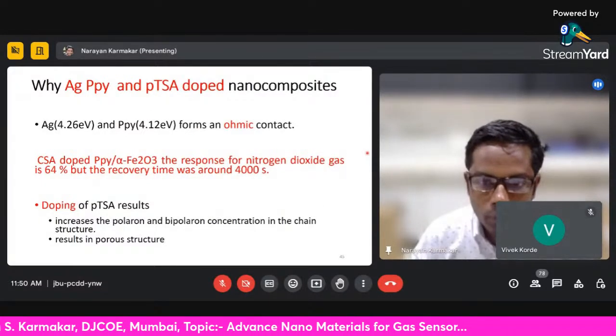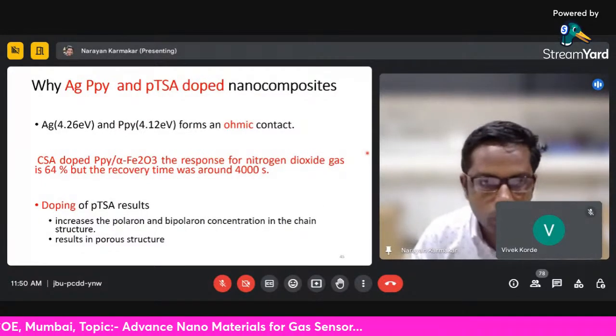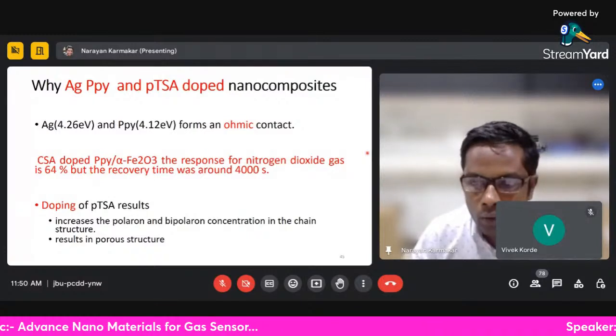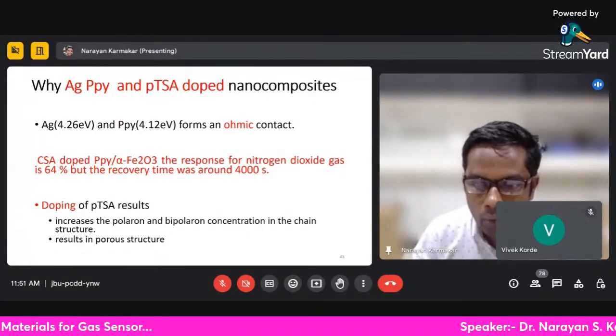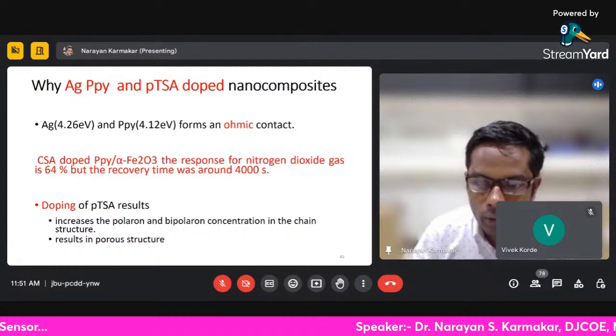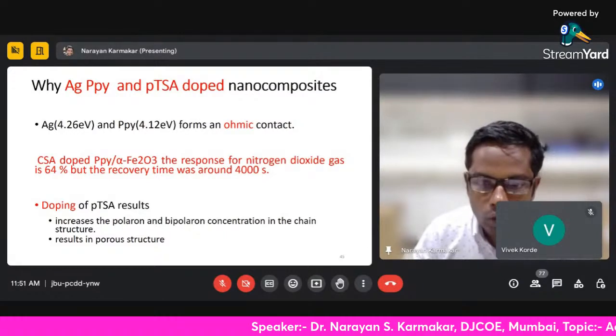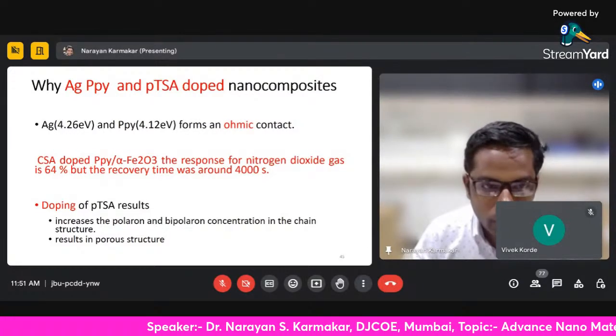Polypyrrole is a conducting polymer with a work function of about 4.12 eV, while silver has a higher work function of about 4.26 eV, so it does not allow the formation of a Schottky barrier.